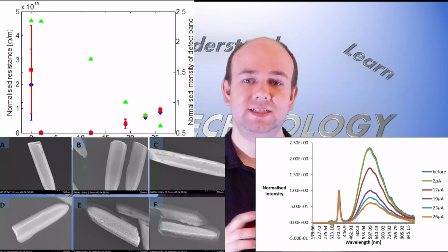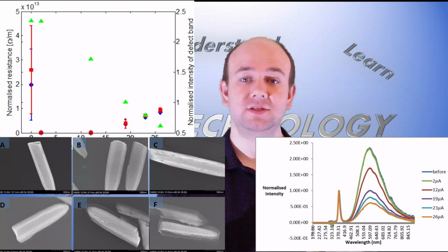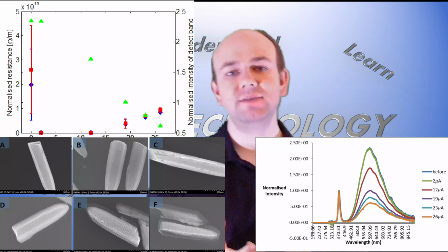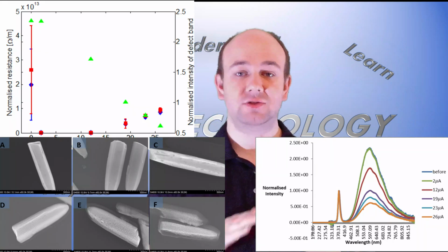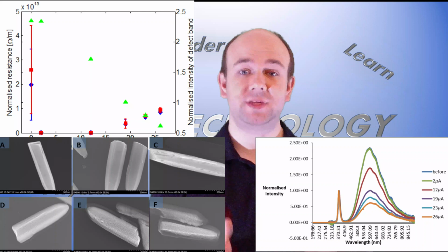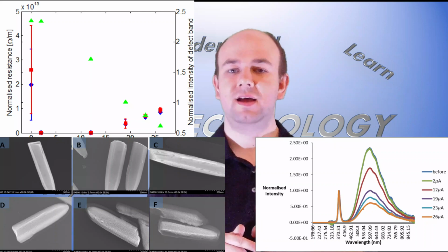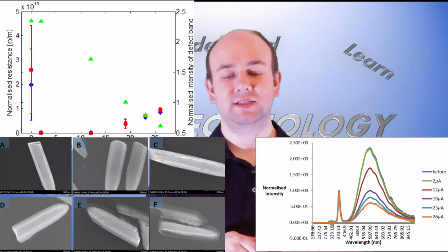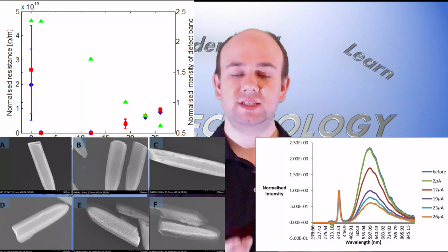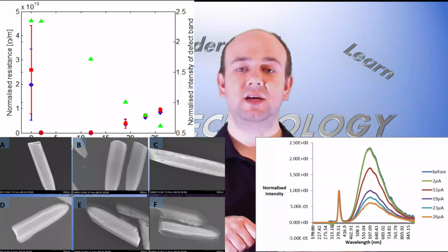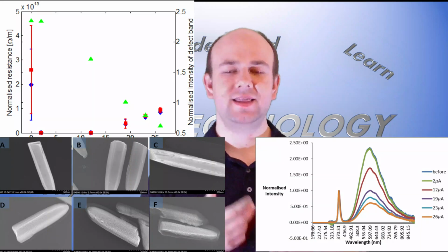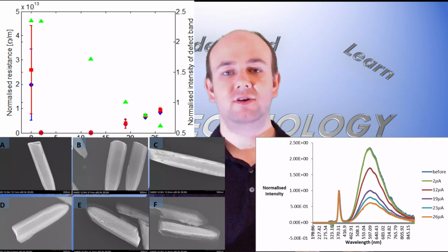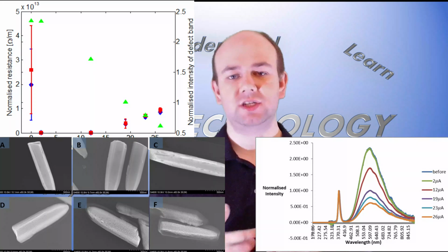So in a crystal structure, the defects make their way out to the surface of the structure, or the near surface, and this is to minimize what's known as the lattice energy. So on a crystal, the actual defects are normally on the surface, and because we've stripped that surface away, we've actually removed the defects. And interestingly, what this does with the conductivity, or the resistance, is as you remove the defects, the resistance starts to go up. So again, this is sort of counterintuitive. You thought if you remove the defects, then your resistance would go down because you have a more pure structure.